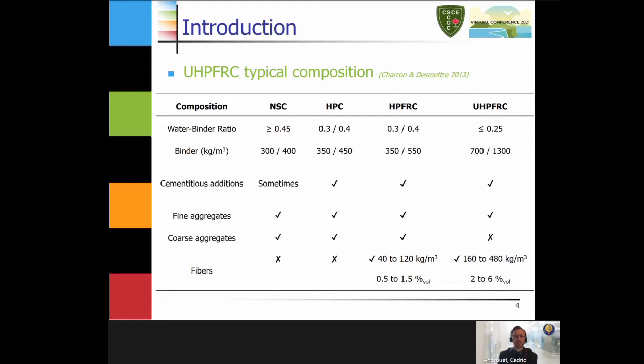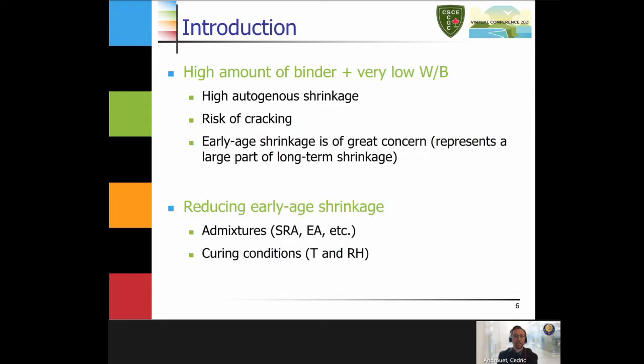If we have a look at this table, what is interesting to see is that we have a very low water binder ratio for UHPFRC, as well as quite a high amount of binder. This means that those materials have a high autogenous shrinkage, leading to some risks of cracking, especially at early age, because the early age shrinkage represents a large part of the long-term shrinkage. So to reduce the early age shrinkage, we have different options. We can use admixtures, shrinkage reducing admixtures, expansive admixtures, etc. And we can control the curing conditions, temperature and relative humidity.